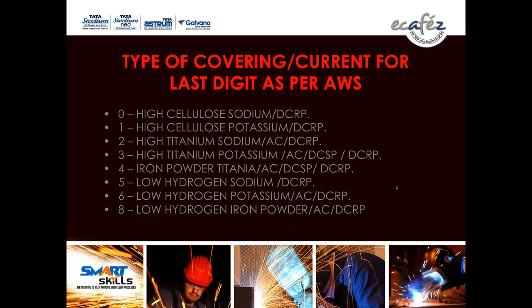If the last digit is 3, high titanium potassium is the coating, and this electrode can be used in AC, DCSP and DCRP also. If the last digit is 4, iron powder titanium, it can be used in AC, DCRP and DCSP also. If the last digit is 6, this is a low hydrogen electrode, low hydrogen potassium, and can be used in AC and DCRP. If the last digit is 8, this is also a low hydrogen iron powder electrode and can be used in AC and DCRP also. Is there any question?